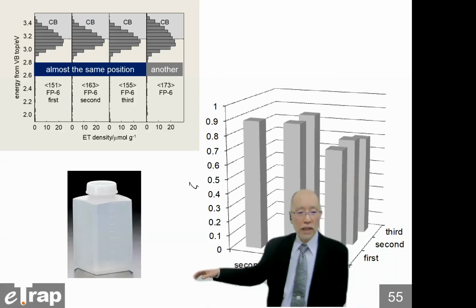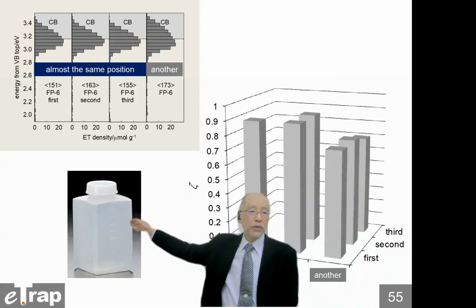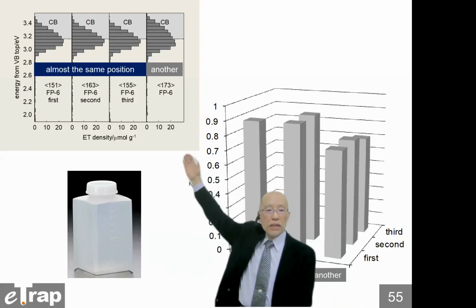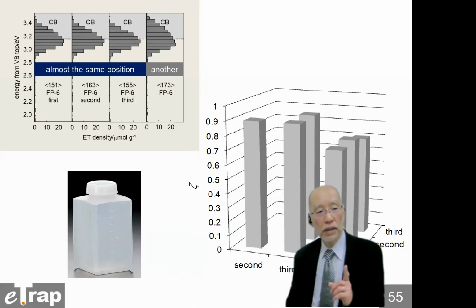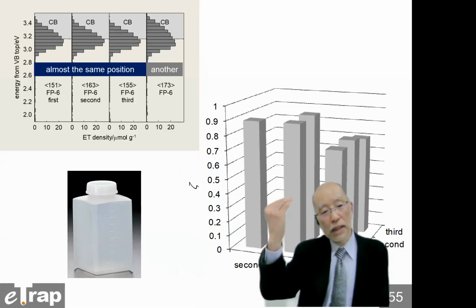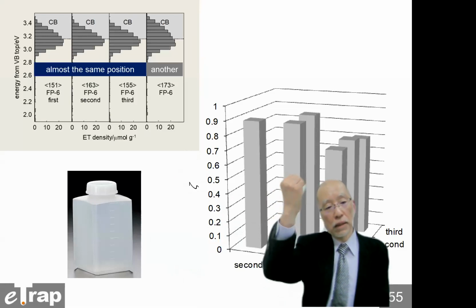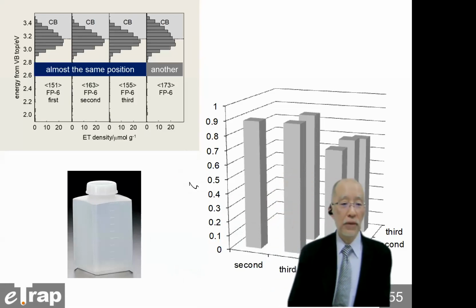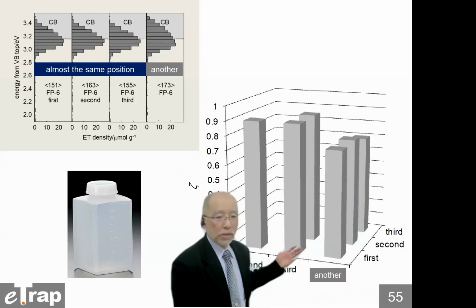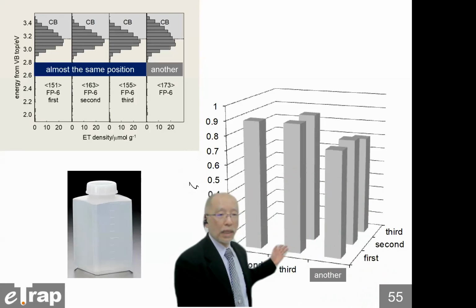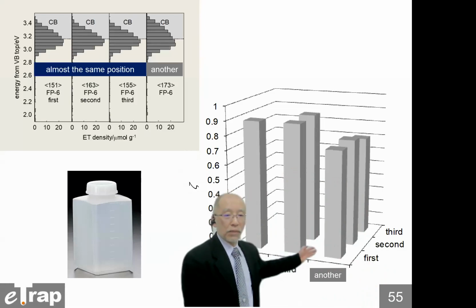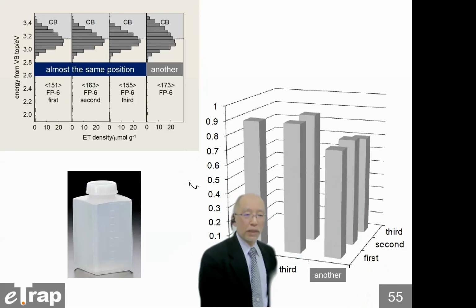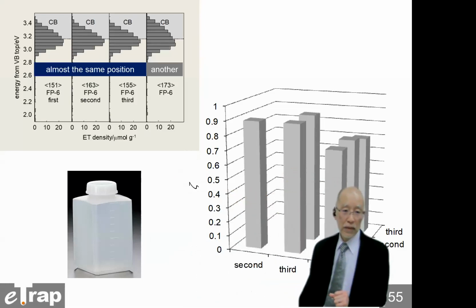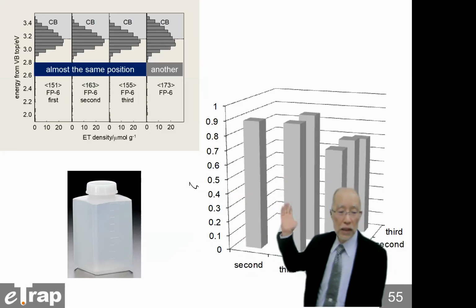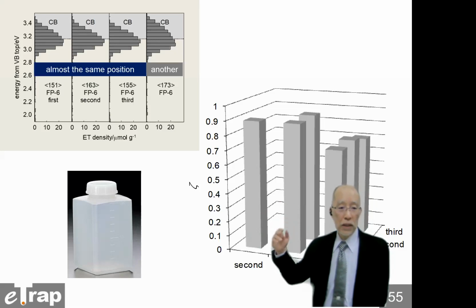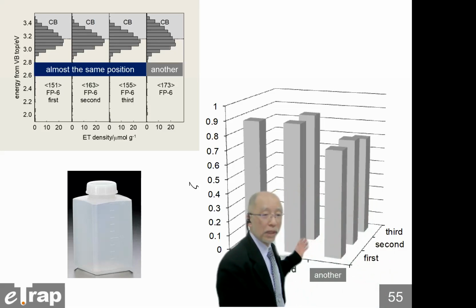Yes, but if the sampling was made from a bit different portion, even in the same bottle, the other pattern gives clearly different ET patterns. So a higher energy side tailing or some peak appeared. And actually, the degree of coincidence of this other sample with the standard sample was a bit lower, about 0.7 or 0.8. So compared with the approximately 0.9 value, that is clearly different, clearly low.